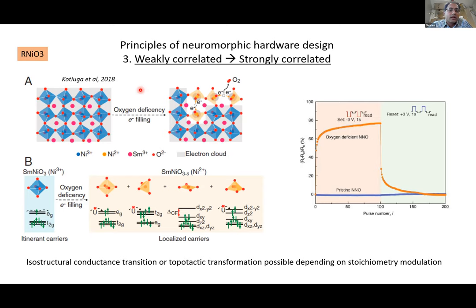So you can introduce correlation by a few different techniques. You can, for example, create oxygen defects. And the most fascinating property of this class of materials is that when you introduce oxygen defects, you make the material more insulating. So this is almost exactly the opposite of what happens in most oxide systems, where the charge carriers due to oxygen defects will go into the conduction band. Here you can have localization of carriers.